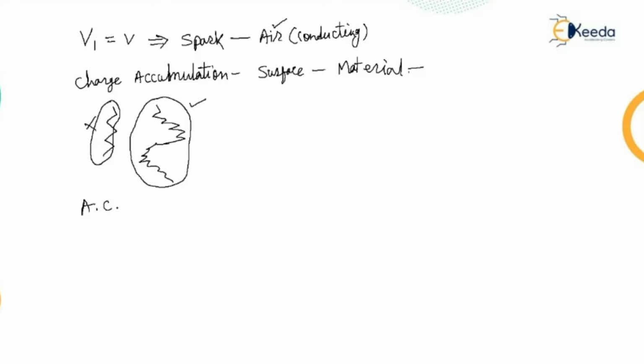Under AC voltage conditions, treeing can occur in a few minutes or may take several hours. Hence, care must be taken to see that no series air gaps or other weaker insulation gaps are formed. Tracking occurs even at very low voltages, say 100 volts, whereas treeing requires some high voltage. Tracks are nothing but crack formation, dry tracks due to the continuous heating of that insulation. But whenever we have continuous application of higher voltage, the chances of formation of a tree become higher, and that follows the weakest path between the gap of the electrodes.